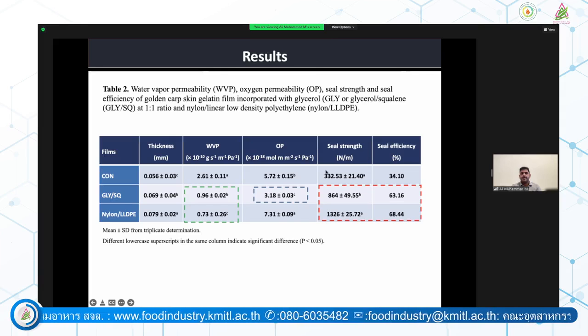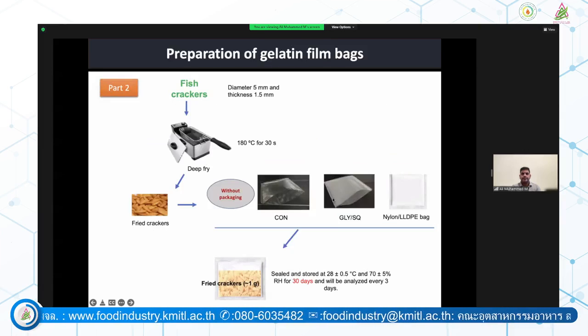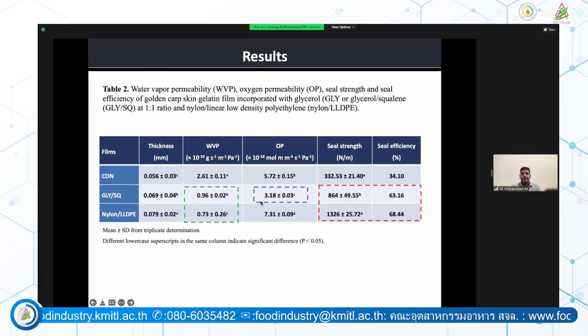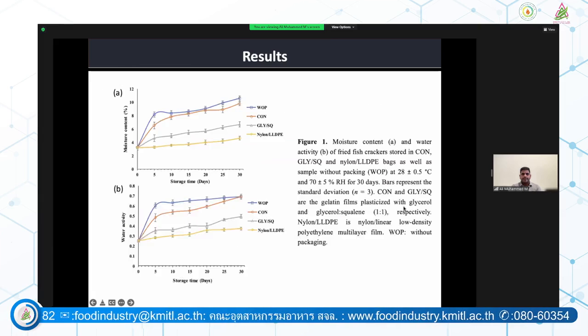Further, the sealing ability at the joint of the packaging. We can see the squalene joints have good sealing ability compared to the conventional gelatin packaging. And the seal strength was higher for the squalene incorporated packaging compared to the conventional gelatin packaging. And the highest was observed for the commercial nylon packaging. So the highest sealing efficiency was for the commercial packaging. And we can see the storage studies.